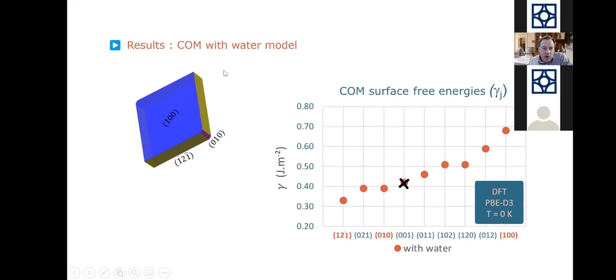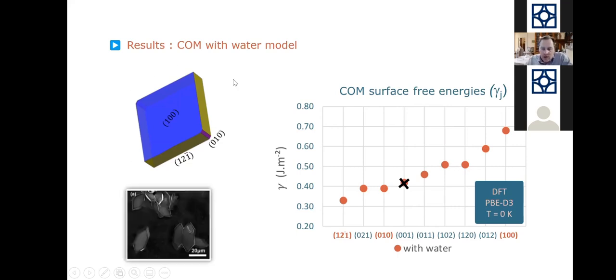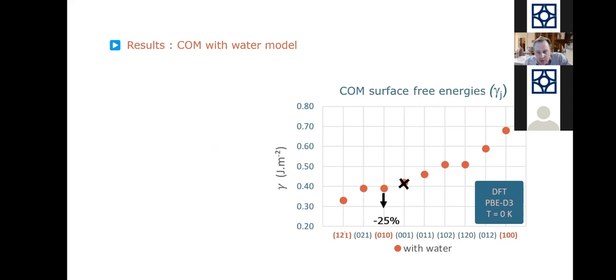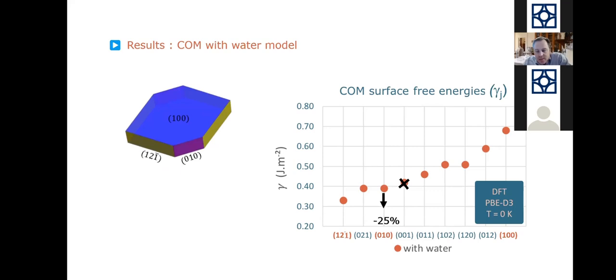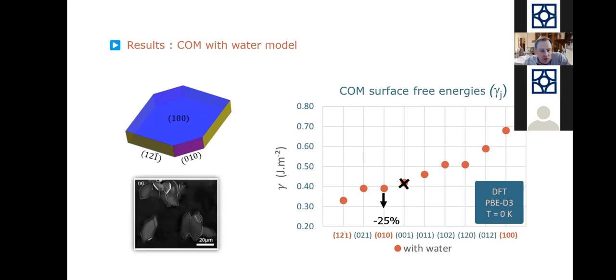But we are still not happy, as you see, because what we want is this type of crystals, hexagonal. So there is something else. We need to grow this 0, 1, 0 surface. And how do we do that? Well, in fact, it is by lowering its energy, making our 0, 1, 0 surface more stable. And this is something that we see. So if we do that, we obtain the structure which is reasonable.